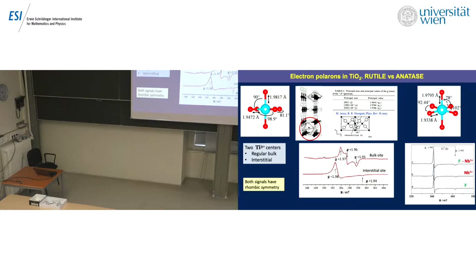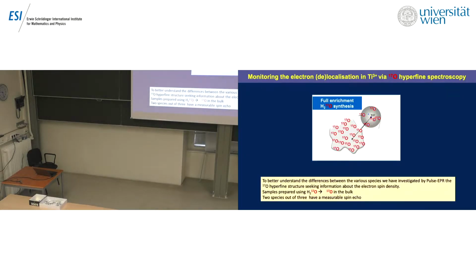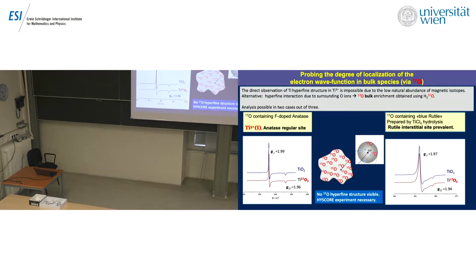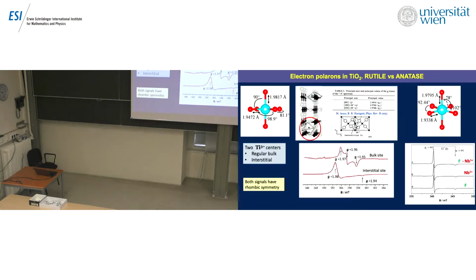We have to rely, once again, on pulsed EPR and, in this case, on the oxygen-enriched system in the bulk, so the second type of enrichment. The first problem is that for the main site of rutile it has not been possible to measure the spin echo. It's a question of relaxation time. It's not our fault, it's the fault of the system.